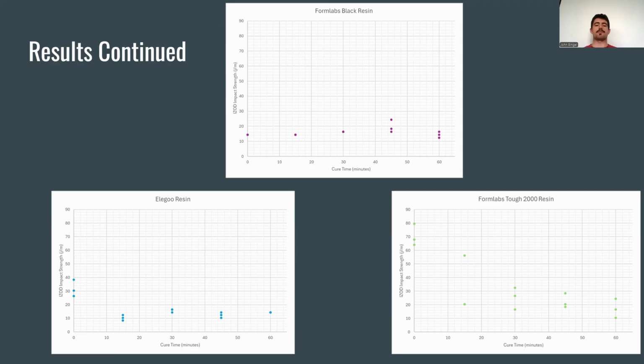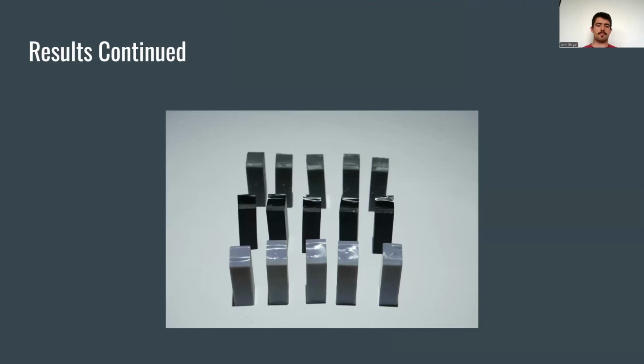The average IZOD energy for no cure Tough 2000 was 70.45 joules per meter and 17.07 joules per meter for the 60-minute cure time. All the test samples demonstrated brittle fractures, with a clear trend towards more brittle fractures, following the same trend as the impact energy for each resin, such that the Tough 2000 samples become much more brittle, the Elegoo a little more brittle, and the Black not noticeably more brittle in the fracture pattern.